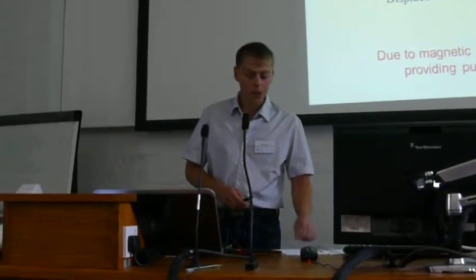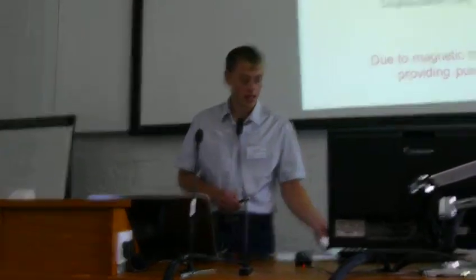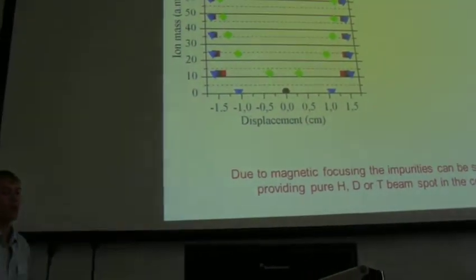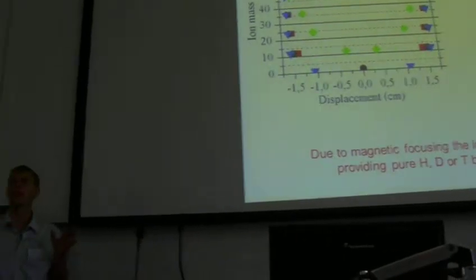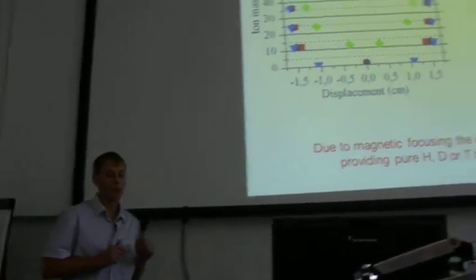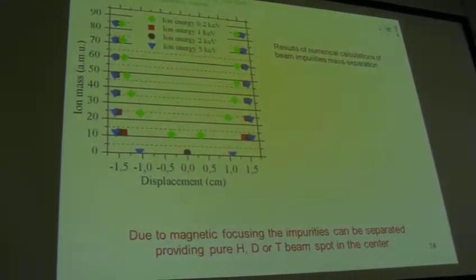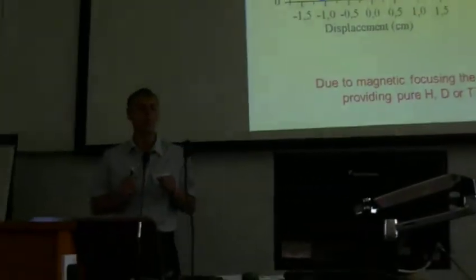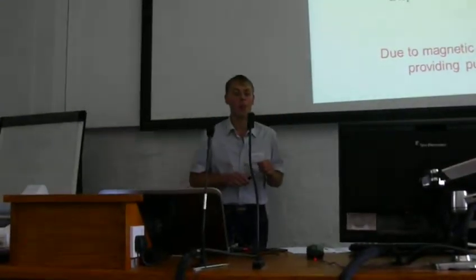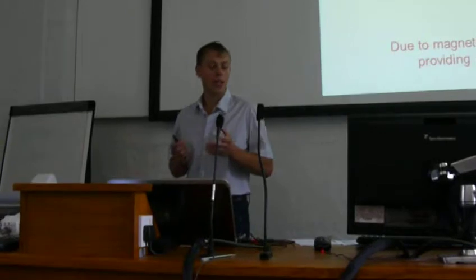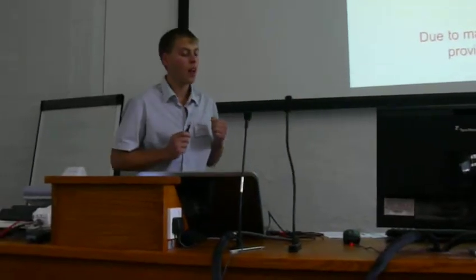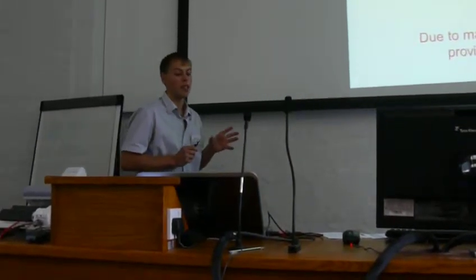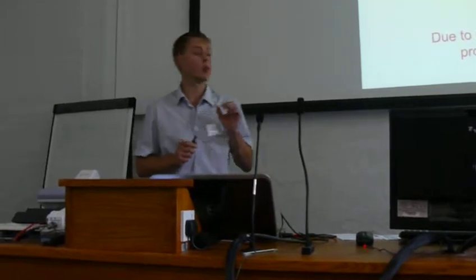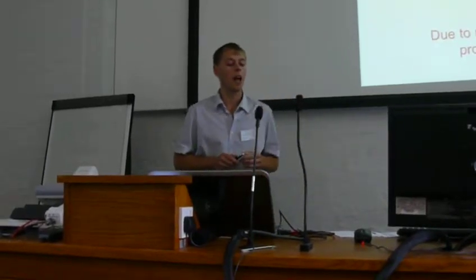The sputtering coefficients of hydrogen ions and such impurities as nitrogen and oxygen differ by nearly 50 times. So, a small percentage of impurities in the beam can significantly distort the result. This necessitates ion trajectory calculation. Ions of different energies have different deviations in the beam crossover plane.